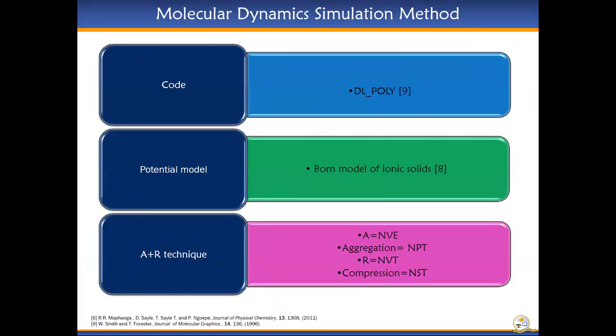Simulated amorphization and recrystallization technique based on molecular dynamics using the DL-Poly code and the Born model of ionic solids were employed to amorphize and recrystallize three Li-Mn2 nanoporous structures of lattice sizes 75, 69, and 67 angstroms at different lithium concentrations, where the NVE ensemble was used for amorphization, NPT for atom aggregation, NVT for recrystallization, and NST for compression.